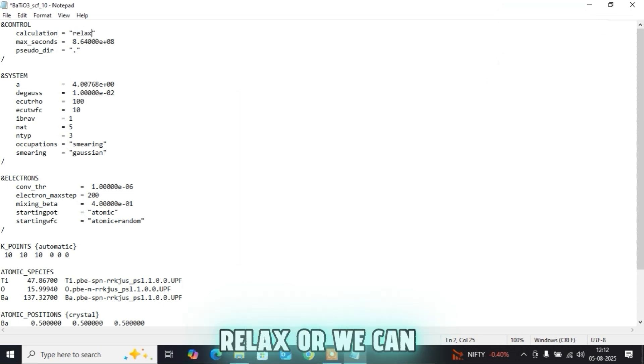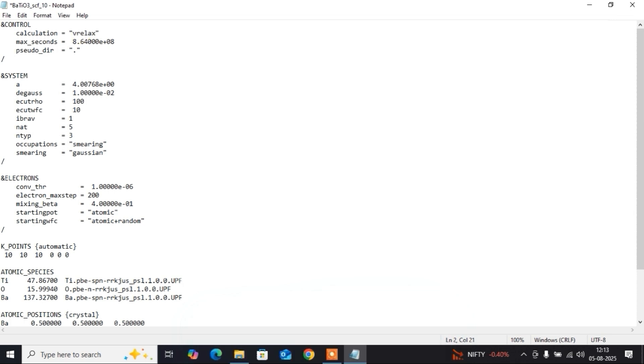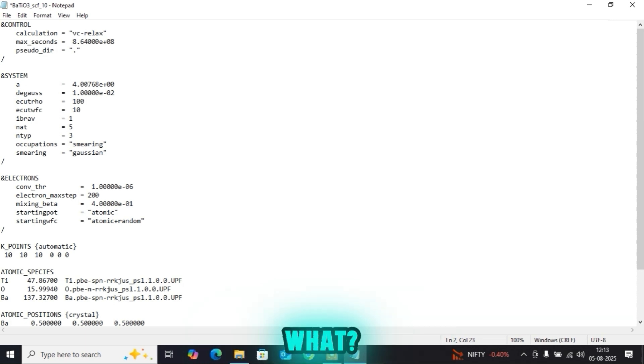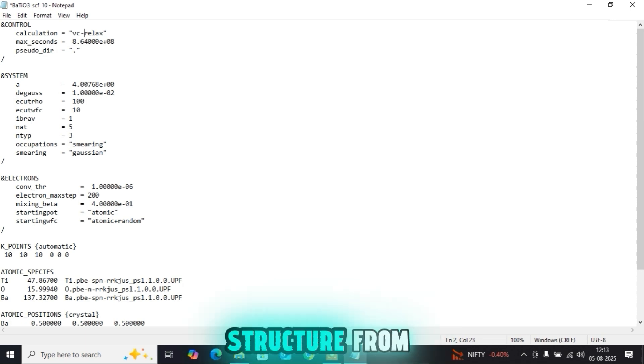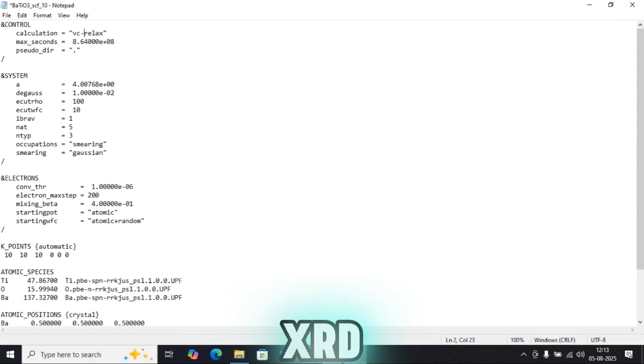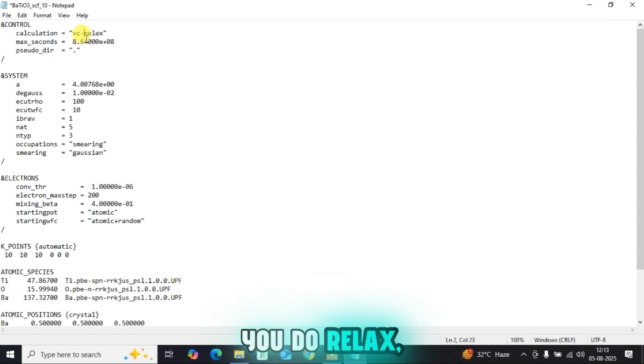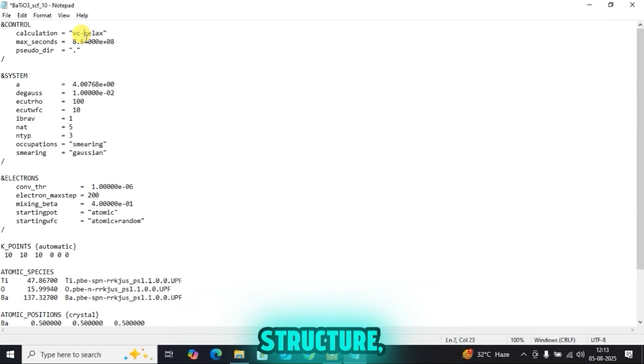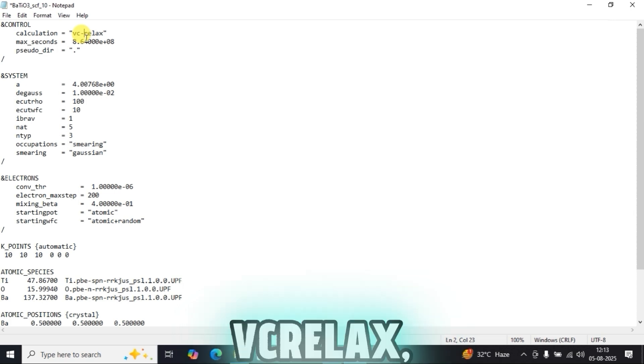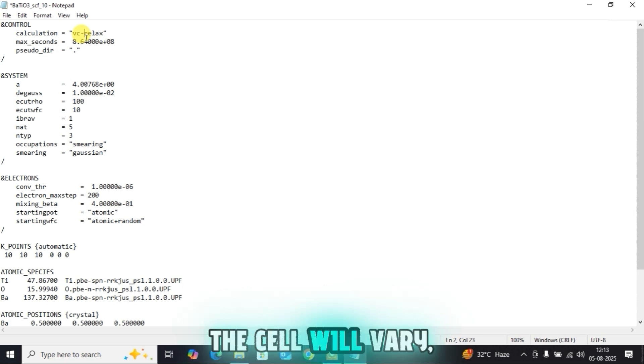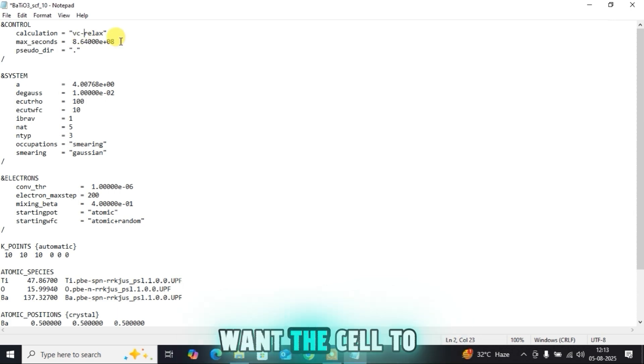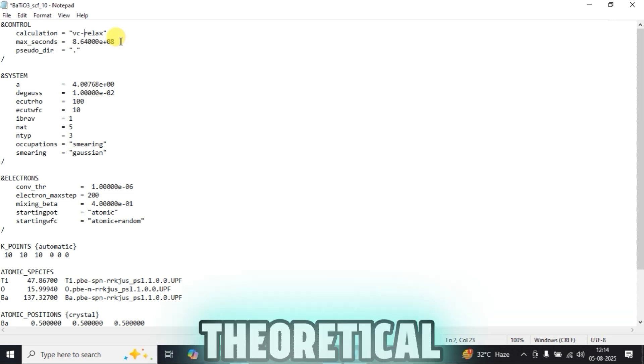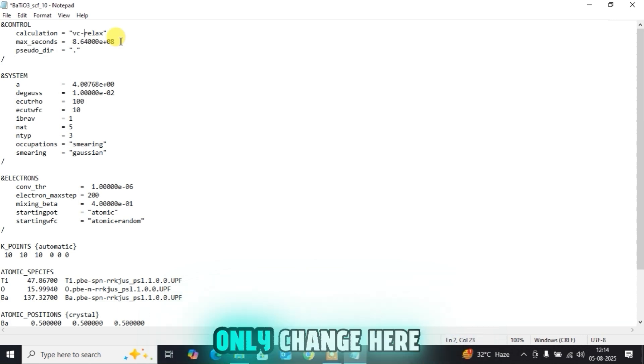We can either do 'relax' or 'vc-relax'. Remember, when you are doing vc-relax there is a hyphen between vc and relax. Simply speaking, if you have a structure from experiment — from XRD data or Raman — you do relax, not vc-relax. But if you have a whole new structure without an experimental reference, you must do vc-relax. VC stands for variable cell — the cell will vary. You don't want the cell to change if you already have an experimental structure.